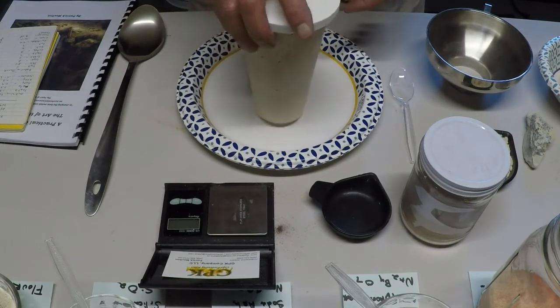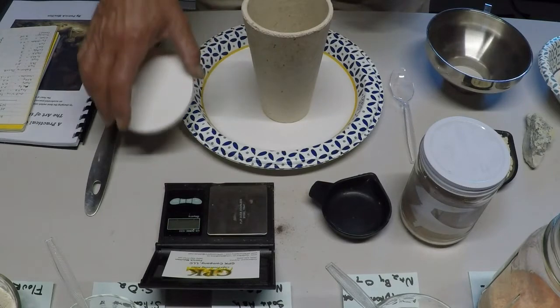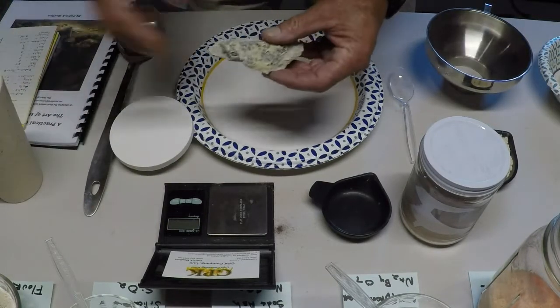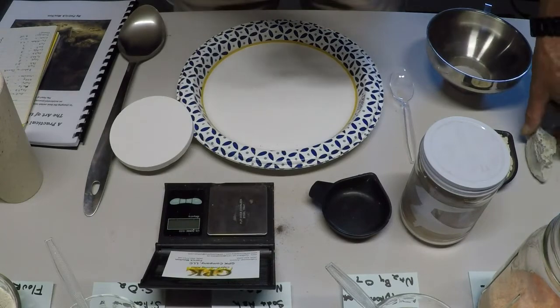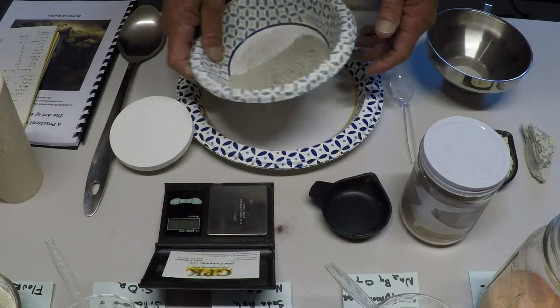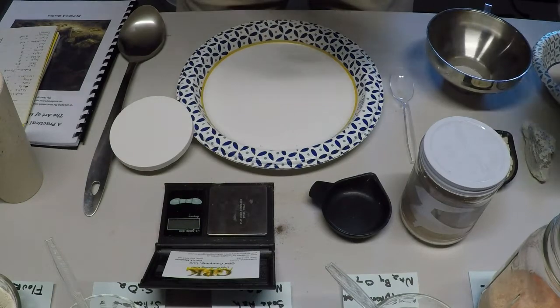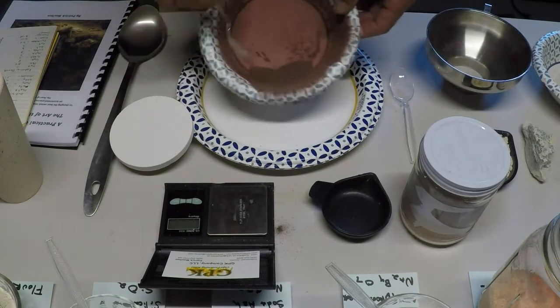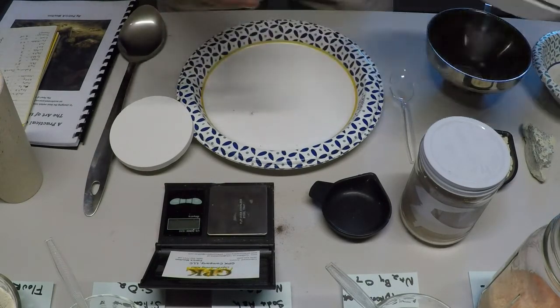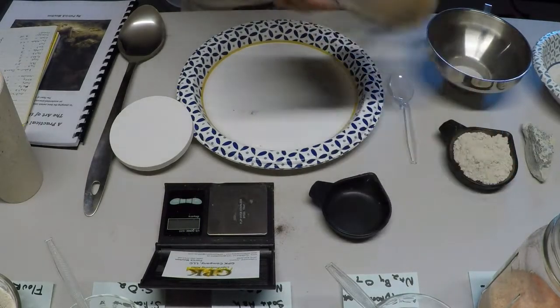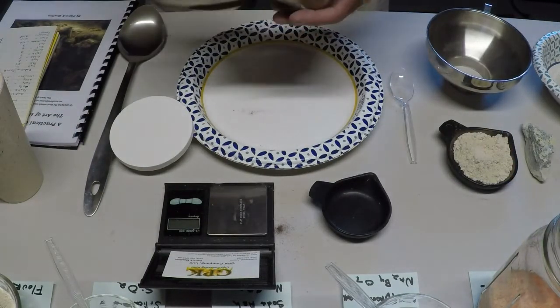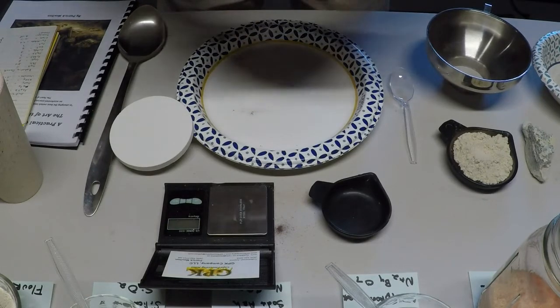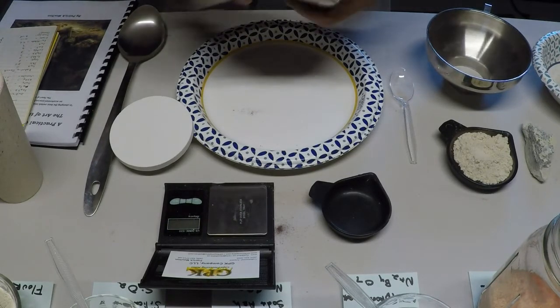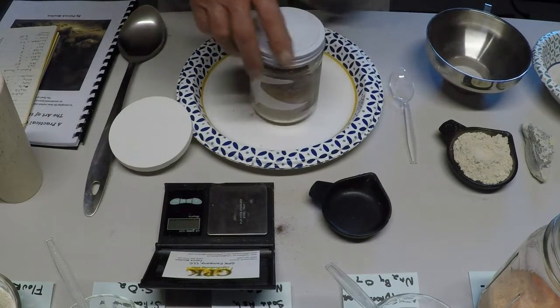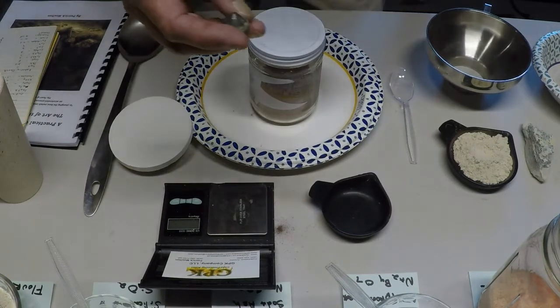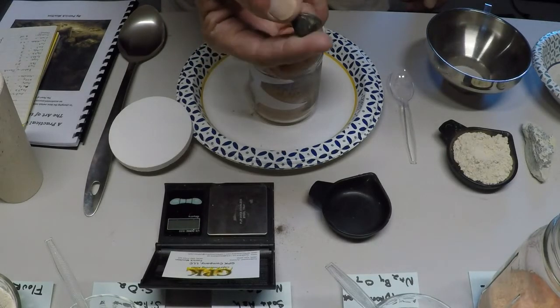So, having said that, we went through the steps, took our ore, crushed it, concentrated it. We ended up with this. We roasted it, concentrated it again, ended up with this material. We just took 30 grams of that material, mixed it with all of our flux components, and mixed them all together along with the flour necessary to produce a lead prill of approximately 30 grams. And there is our lead prill.